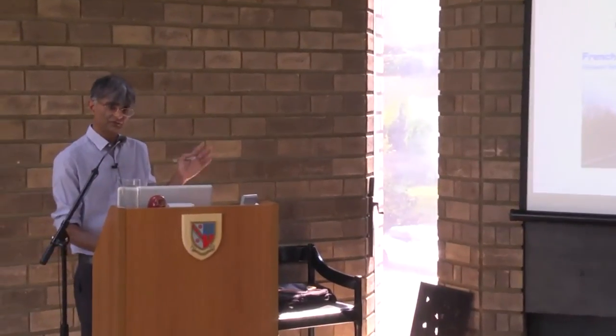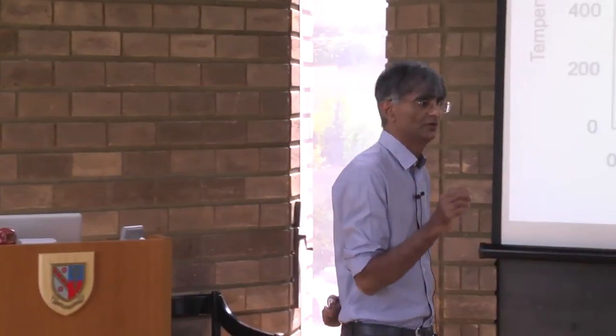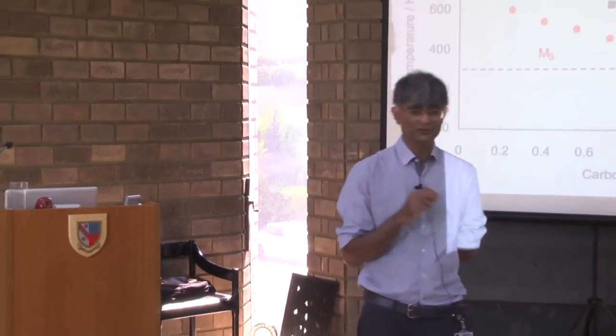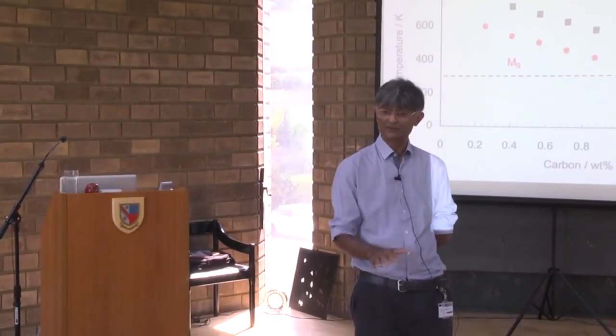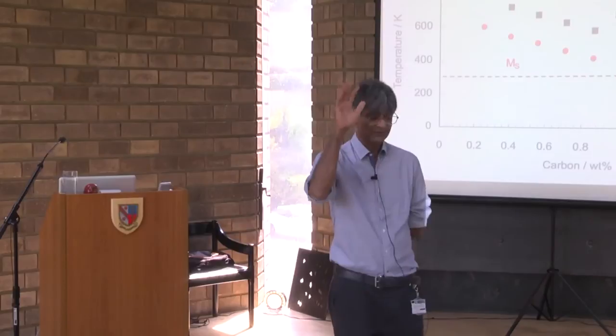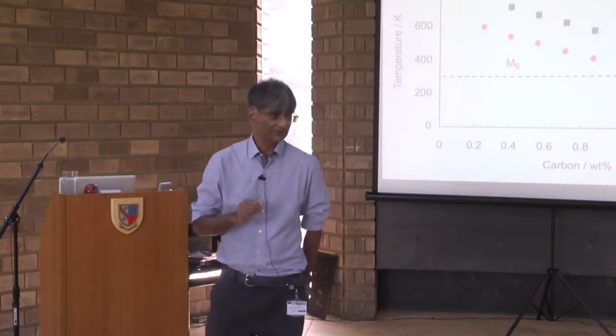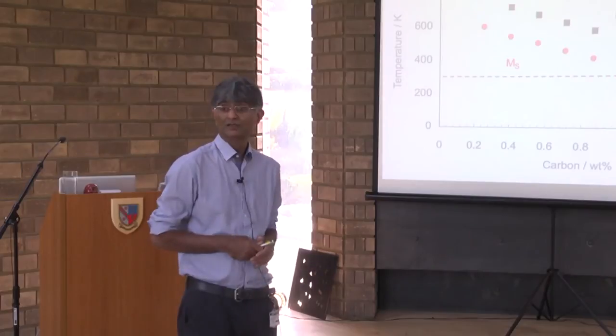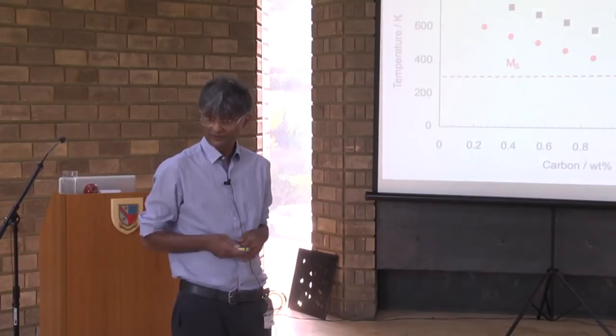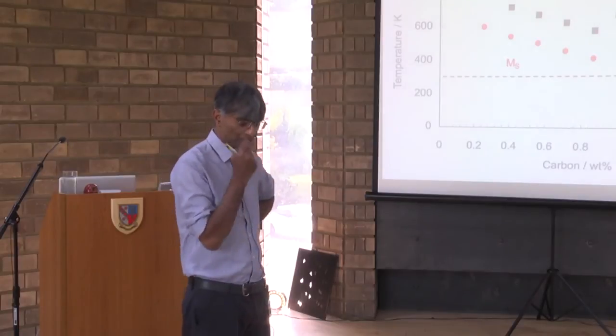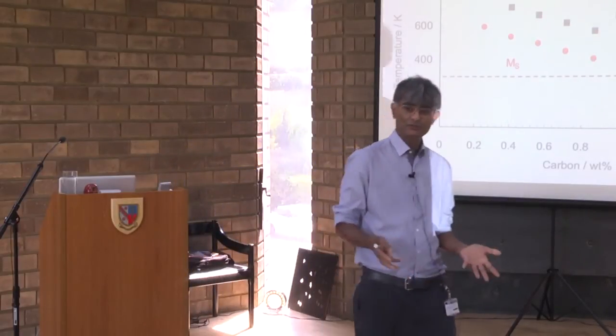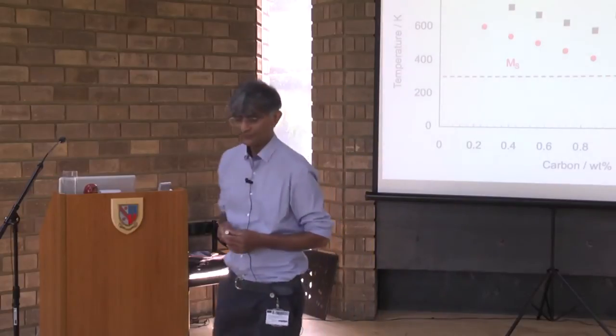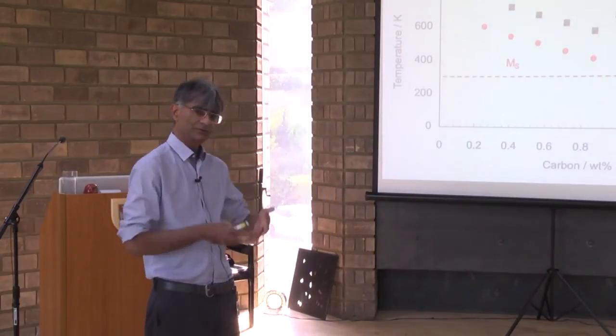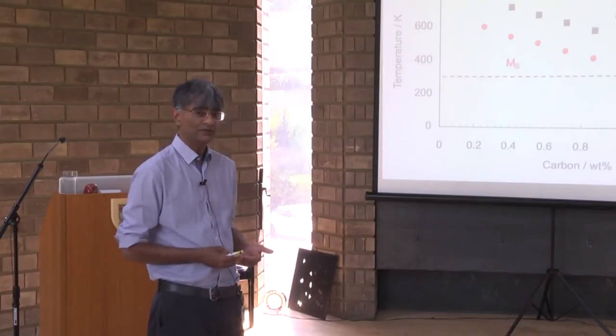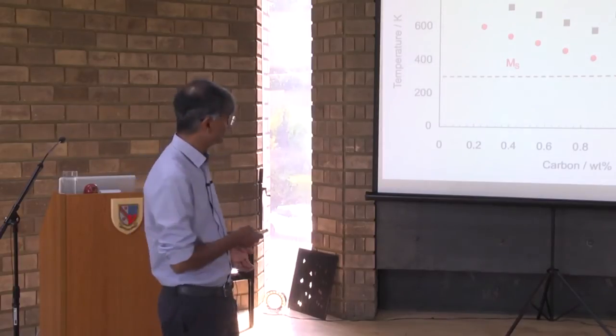But the strength level here is not as high as we want. Now, I said to you that we want to create fine crystals, and to create even finer crystals, we need to form them at a low temperature, okay? Bearing in mind that steel melts at about 1560 degrees centigrade, a low temperature would conventionally be about 400 degrees centigrade. But we wanted to find out whether there's a theoretical limit to the temperature at which we can form these crystals. And there is one further problem, is that if you cool to an even lower temperature, you get a very brittle crystal forming called martensite.